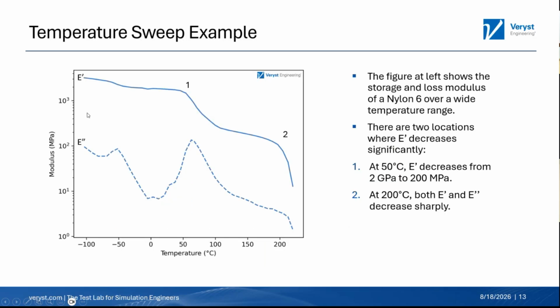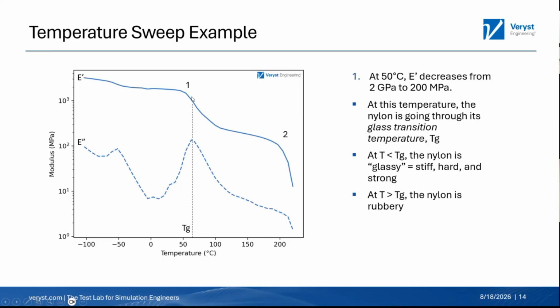of test where you're measuring the storage modulus, which is essentially the elastic modulus of the material, and the loss modulus, or E double prime, as a function of temperature. And so this particular example is for nylon 6, which is a semi-crystalline material. And so as we go from minus 100 C up to just above 200 C, I've pointed out two spots that I think are most interesting to the material. So one labeled number 1 and one labeled number 2, both where the storage modulus, essentially the elastic modulus, decreases sharply.